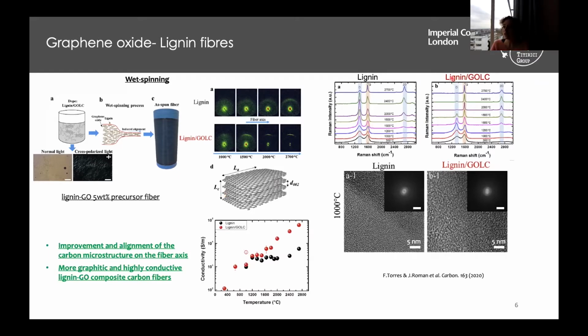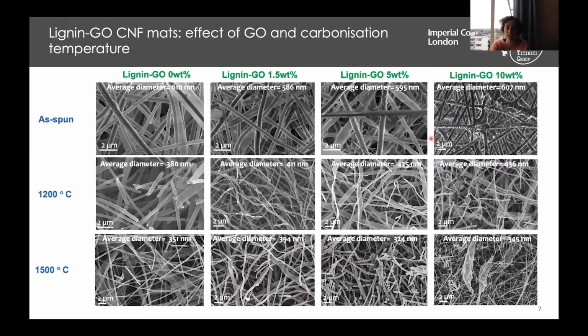Literature has shown how by Raman we can detect that in these materials incorporating graphene oxide, at high temperatures we can obtain very, very ordered structures. And here the TEM shows that even at 1,000 degrees, when we carbonize lignin on its own and lignin with graphene oxide, we obtain much better and ordered structures. So we want to take advantage of this helping effect that graphene oxide produces in lignin to generate more conductive fibers.